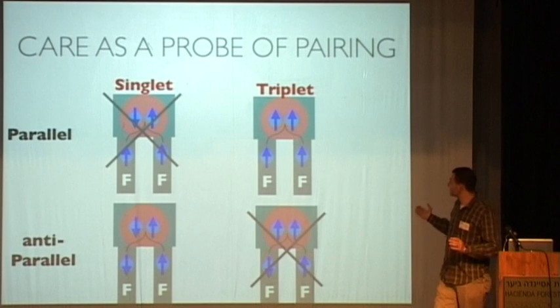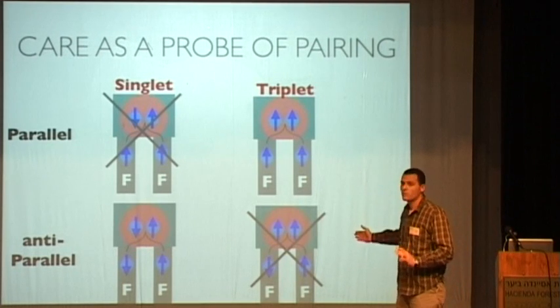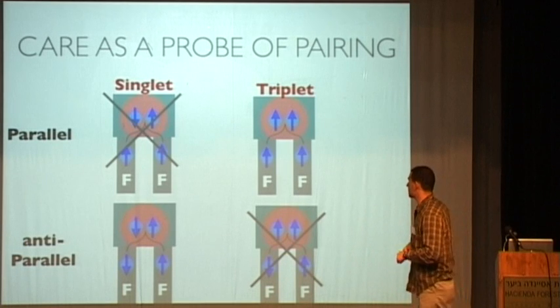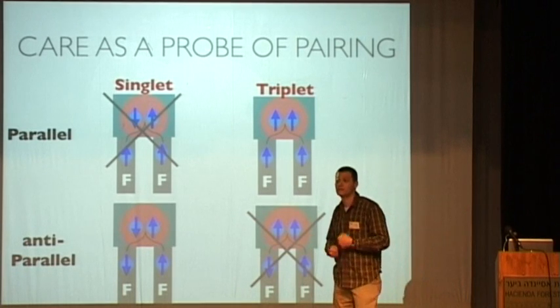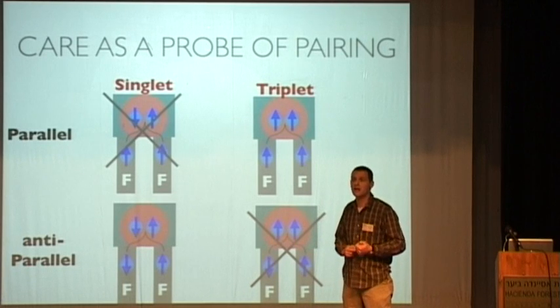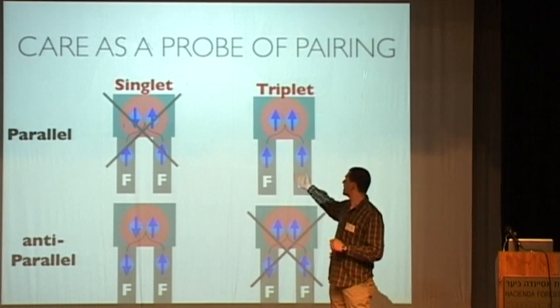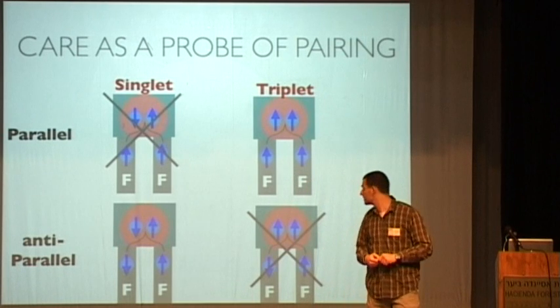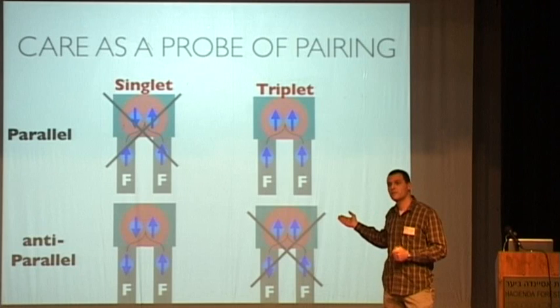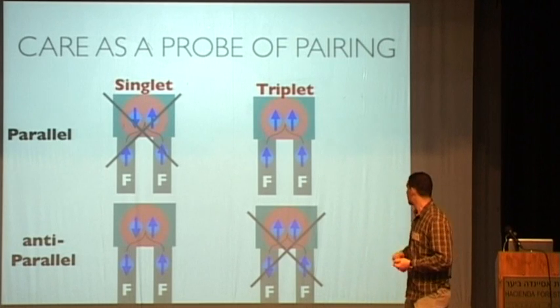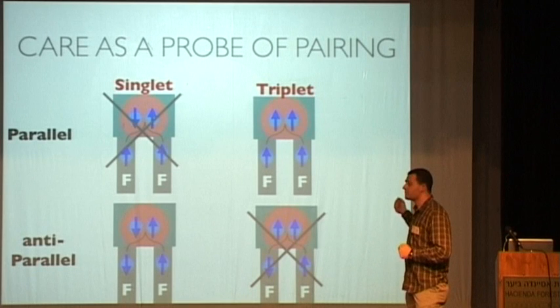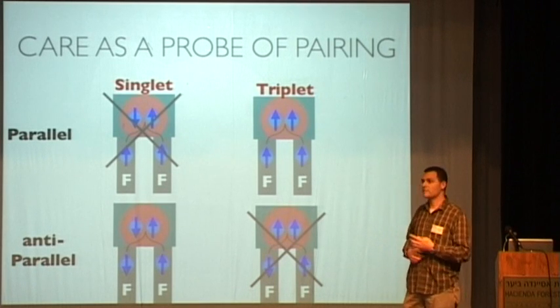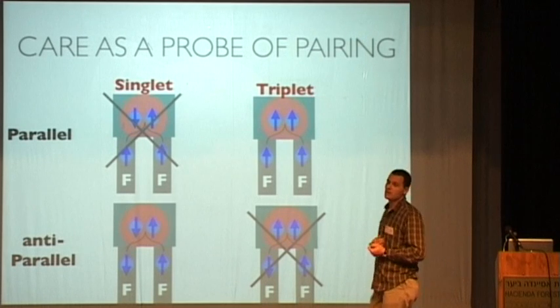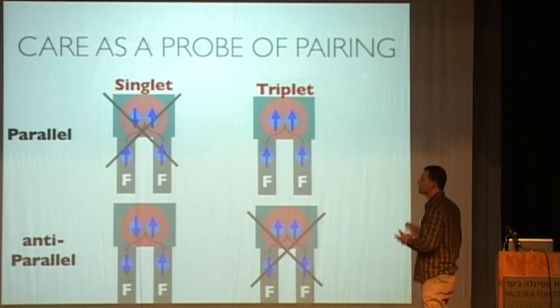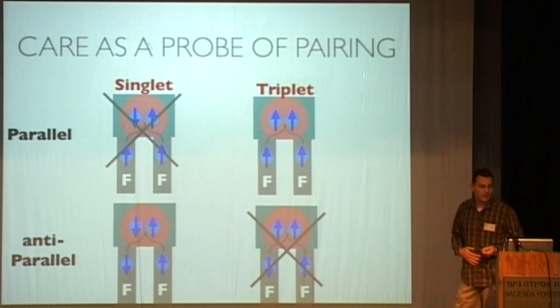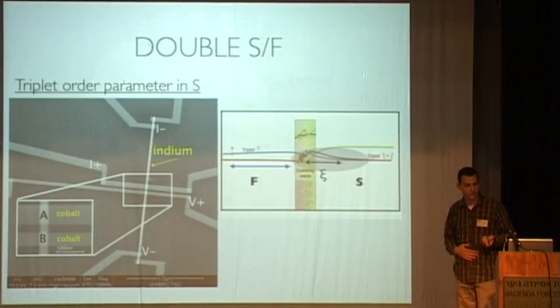It's very simple. Let's consider two cases. First, a singlet, where the Cooper pair has opposite spins. Then, if we assume that the ferromagnet is fully polarized, which means that there are only spin-up electrons, then in the upper case, the cross-Andreev reflection cannot take place. It can only take place if the ferromagnetic leads are anti-parallel to each other. And vice versa in the triplet state. If the pairing is of equal spins, only in the parallel state the cross-Andreev can take place. So this can be used as a tool to measure the type of pairing inside the superconductor.